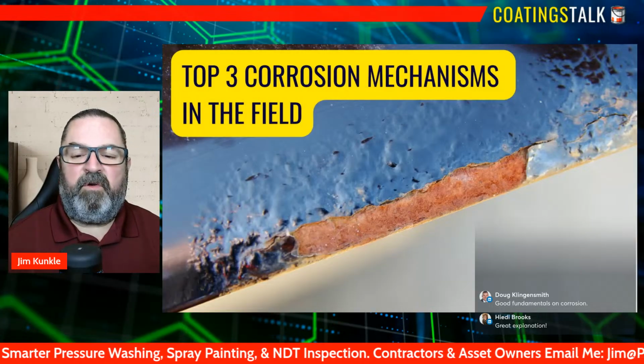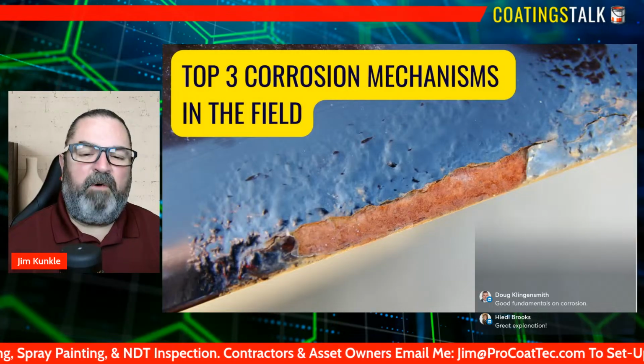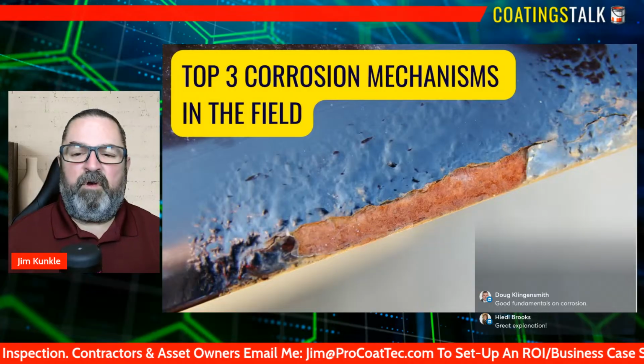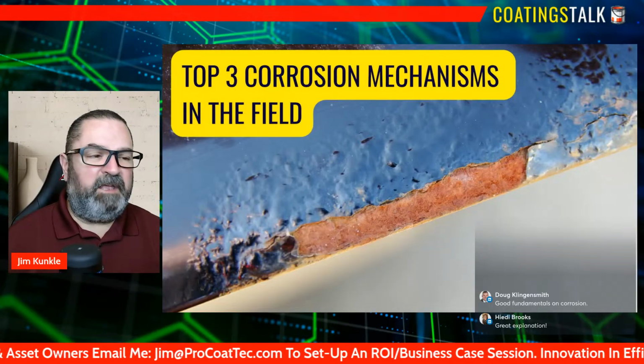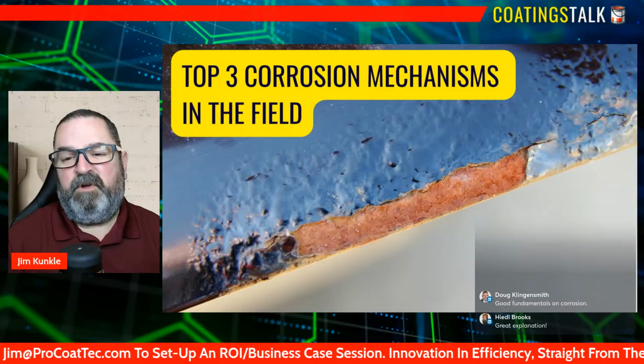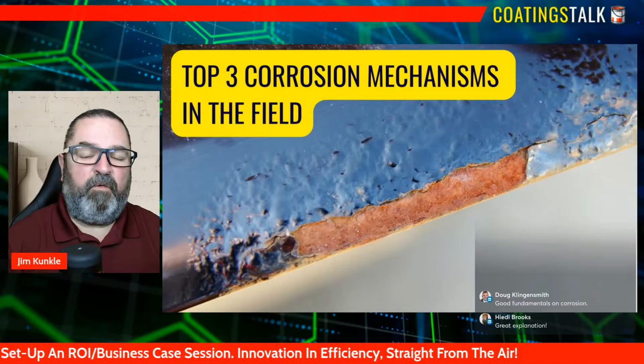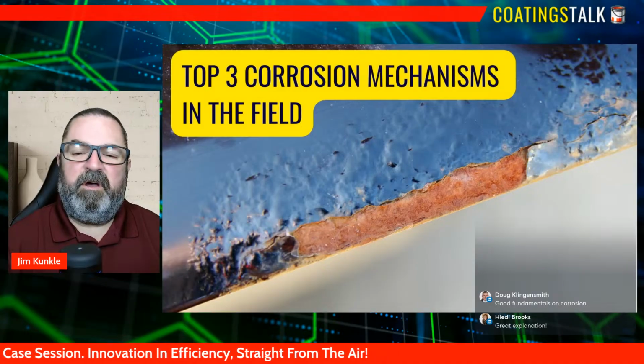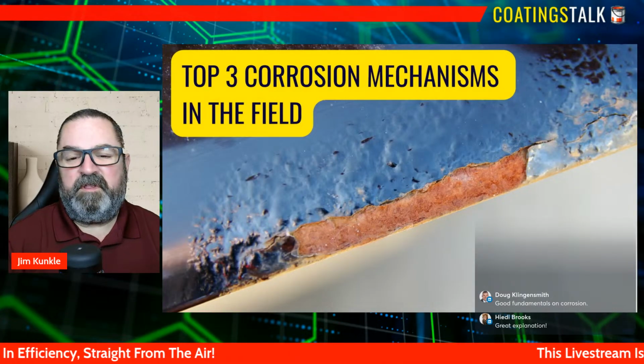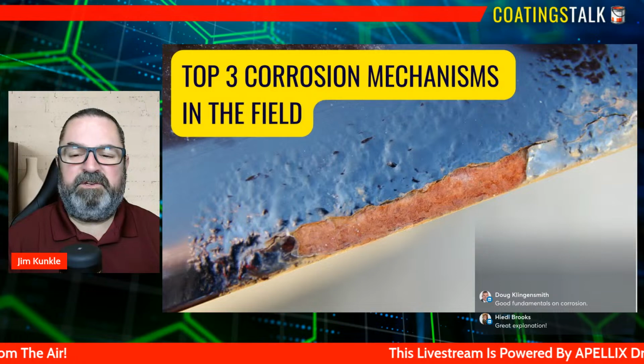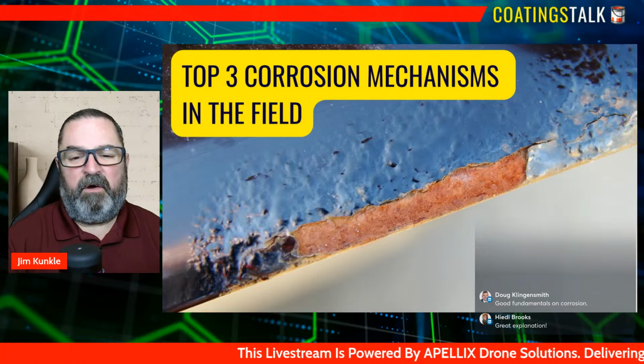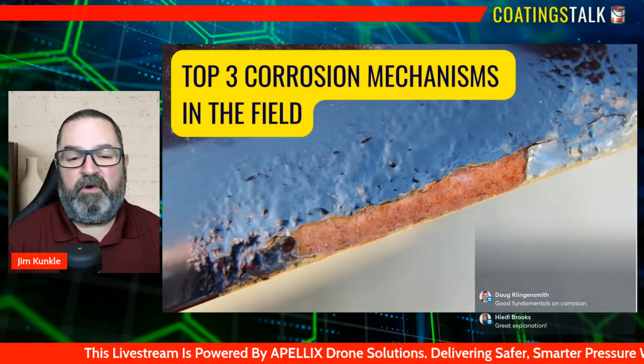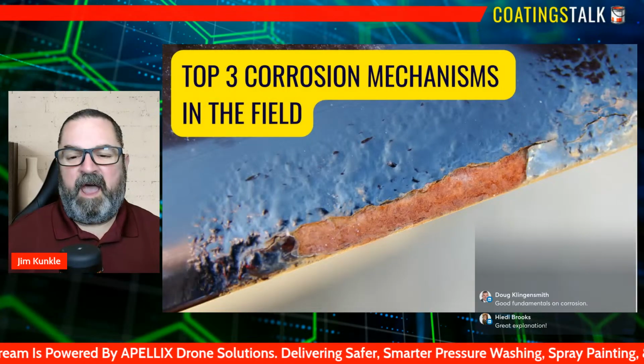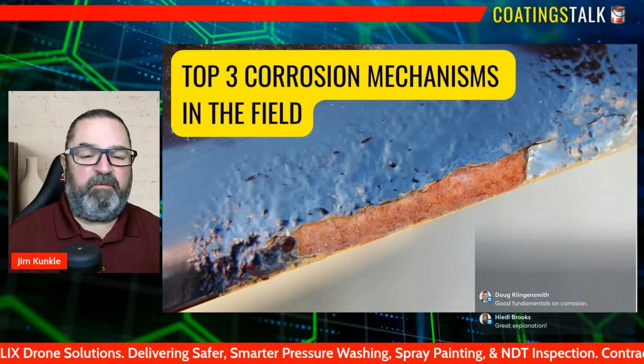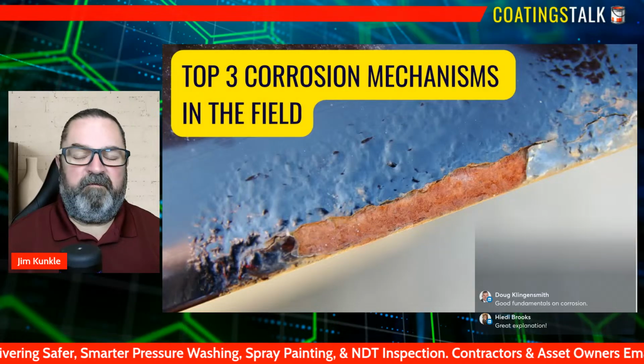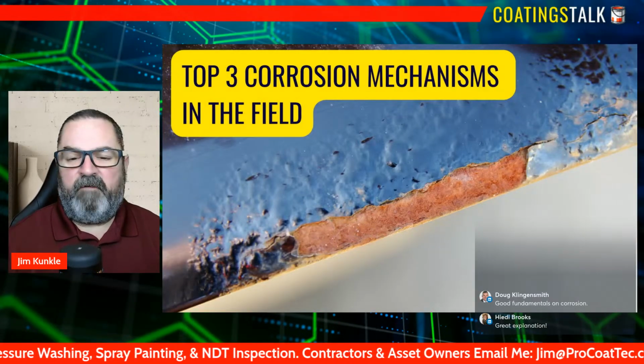What makes localized corrosion especially challenging in the field is how easily it escapes detection. Pitting can form behind coatings, under insulation, behind gaskets, and in tight joints where inspectors can't easily see or probe it. Crevice corrosion often develops where two surfaces meet: lap joints, bolted connections, clamps, or deposits sitting on the metal. These areas restrict oxygen flow, creating a chemical imbalance that drives rapid attack. By the time visible signs appear, the damage may already be severe, with pits penetrating deeply or crevices undermining